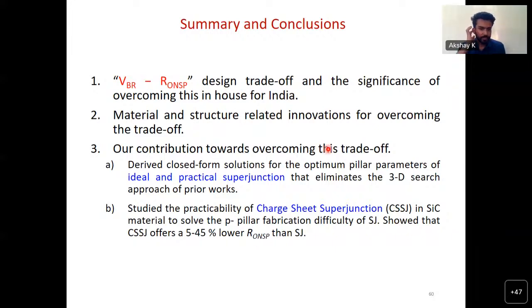These contributions were mainly two. Firstly, we could derive closed form solutions for the optimum pillar parameters of ideal as well as practical superjunctions, and using our solution, we could eliminate the 3D search approach of prior works. We could also propose charge sheet superjunction, a novel device, as an alternative to superjunction in silicon carbide material, thereby solving the P-pillar fabrication difficulty. We could also show that it offers lower specific on resistance by 5 to 45%.